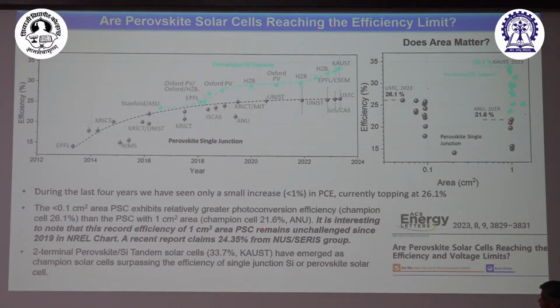If you go into the same table, we get about 21.6%. It is interesting to note that this record efficiency remains unchallenged since 2019 in this chart. A recent report claims 24.35. It is still less than 26.1. So if you are making 1 centimeter square and you are not getting high efficiency, that is one of the reasons.